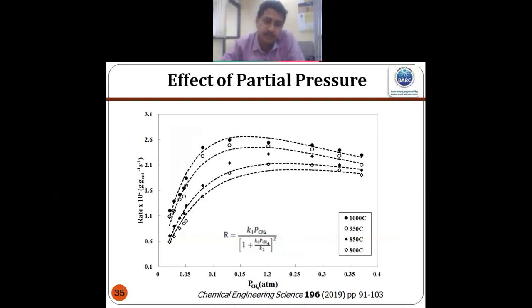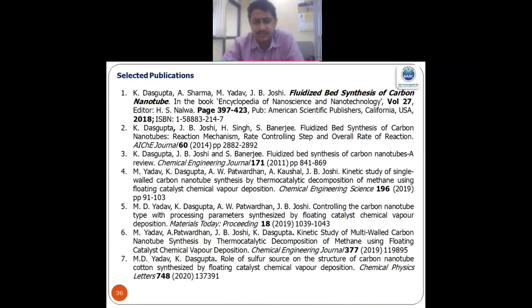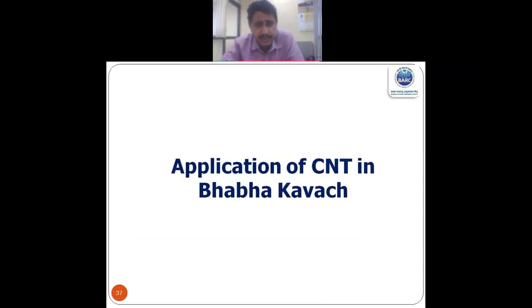So we can produce the multi-wall carbon nanotube at a higher rate, because we can go for a higher hydrocarbon partial pressure. Here we cannot go for a higher hydrocarbon partial pressure. If we go for a higher hydrocarbon partial pressure, we'll end up with soot. These are the selected publications related to that.